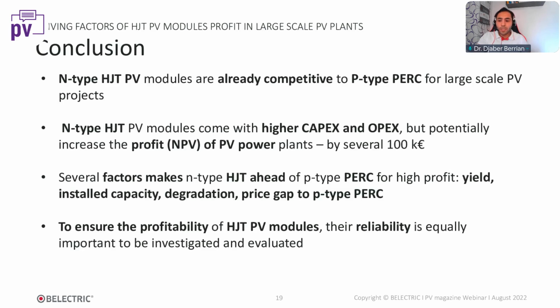To come to a conclusion, we have shown that the N-type heterojunction PV module is already competitive, and even very profitable compared to P-type PERC for large-scale PV projects in Europe. We have also shown that the heterojunction PV module comes with higher capex and opex, but potentially increases the net present value by several €100,000 when we consider the lifetime of the project. And we have shown that several factors put N-type heterojunction ahead of P-type, which are the yield, installed capacity, degradation, and the price gap.